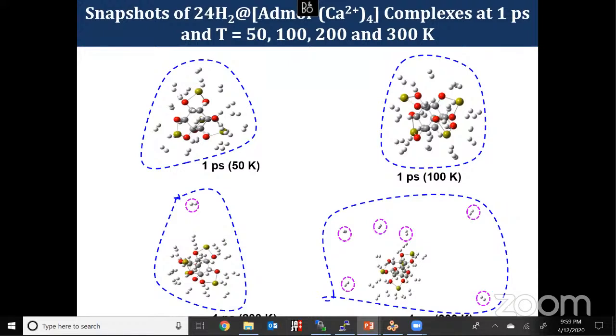So as I mentioned earlier, the radius of the metal and the distance between the adsorbed hydrogen molecule and metals also matter. That also determines whether the hydrogen molecule will tightly bind with the desired binding energy or not. So here, up to 100 Kelvin, there is no desorption taking place. But near 200 Kelvin, there is only one hydrogen molecule desorbed from the moiety. But at 300 Kelvin, a greater number of hydrogen molecules started to desorb.